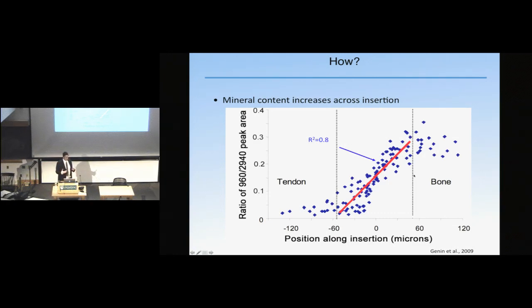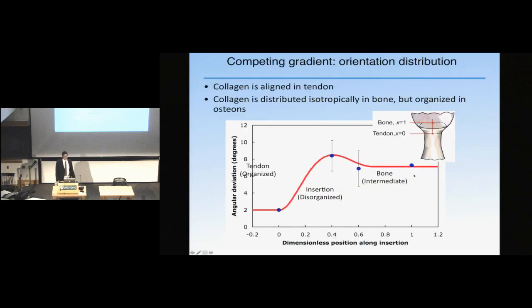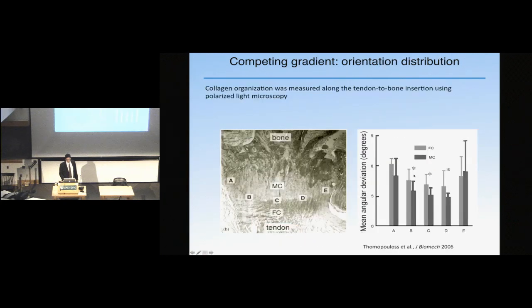This mineral phase is 100 times stiffer than the unmineralized tissue is. And so the hypothesis we tested, that we then looked at orientation distribution using polarized light microscopy, we found that there's also a competing gradient in the orientation distribution of collagen fibers. So the idea is that collagen is a rod-like protein, a bar-like protein, and so it really does best at taking stress along its axis. So there's a competing gradient. And we'll go into how that works in a moment. It's just mentioned that the competing gradient is along the bone to tendon direction, but there's very little difference around the radius of the insertion site.